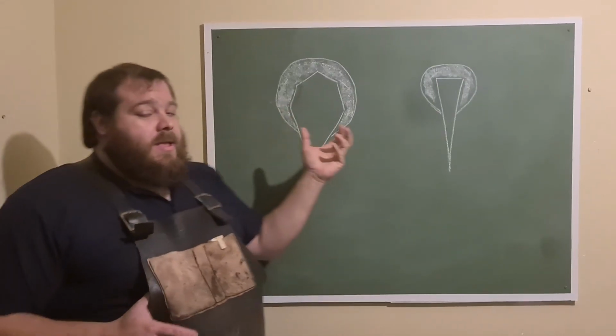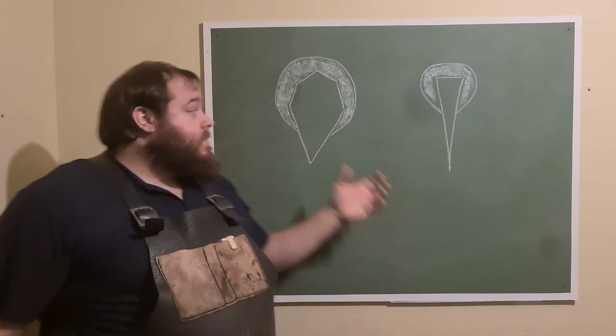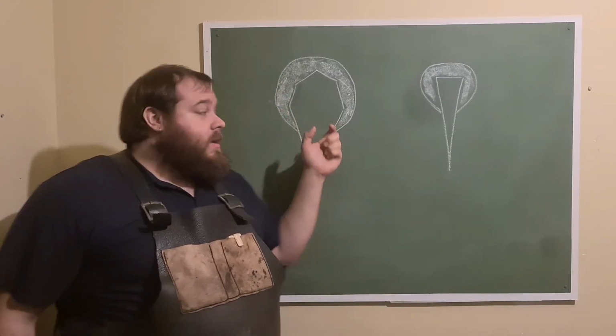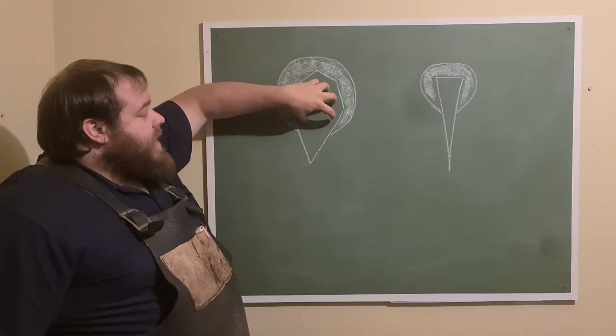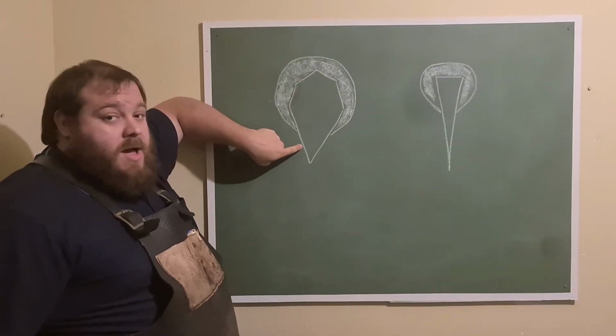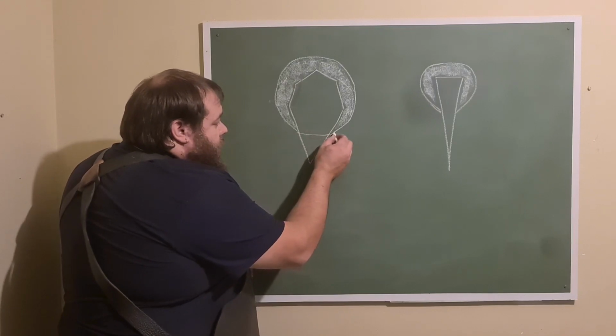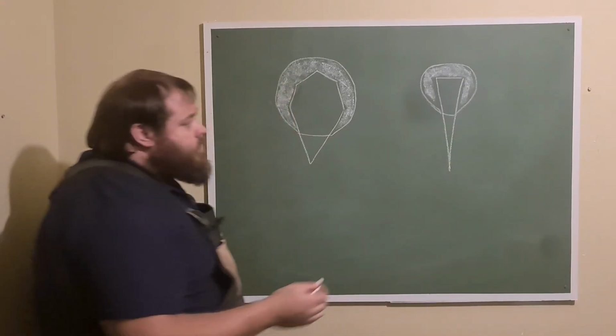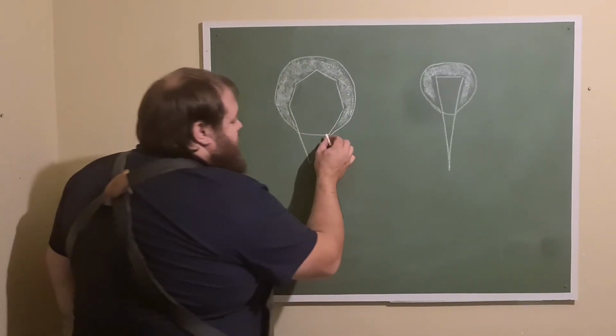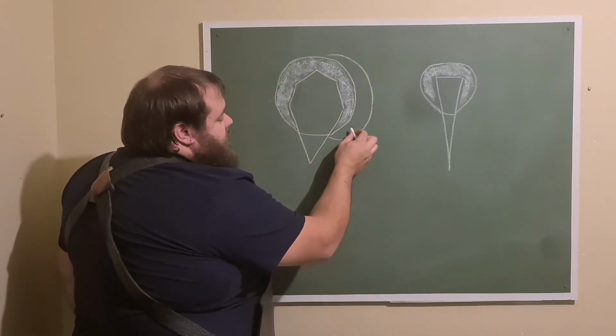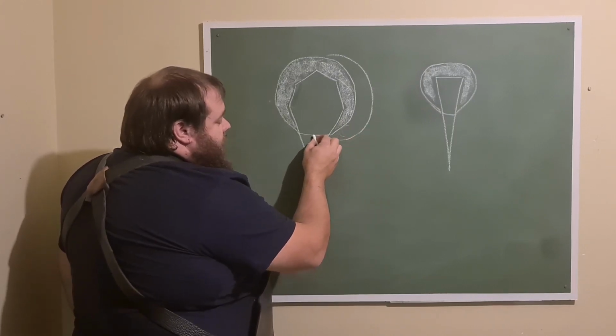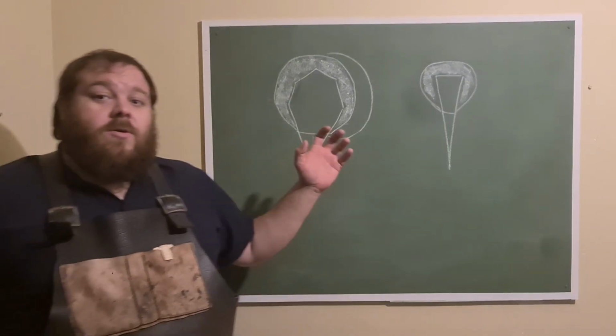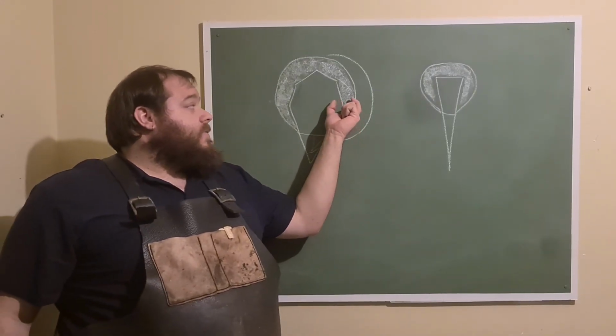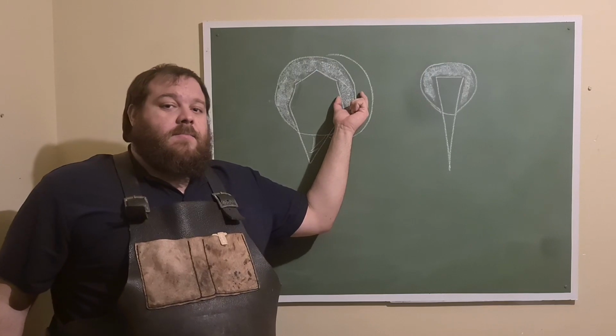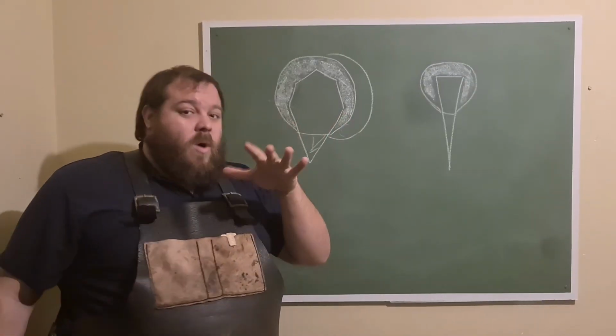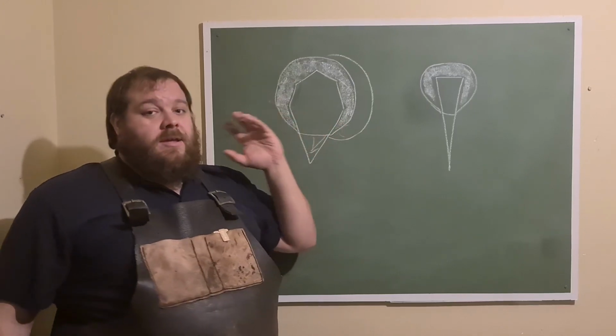You don't want more than that because you're not trying to over-create mass, because the more mass you create, the more heat you contain. Now remember, this is only here to protect this portion of the blade. We want this portion to harden. We want to end up with a hardening line along here, and again along here. That cannot happen if there is excess mass up around here, because what happens is that this extra heat bleeds down into the edge. So what we really need is to make sure that our thickness is increasing the mass by 2 times or 1 2/3 times rather than 3 times.